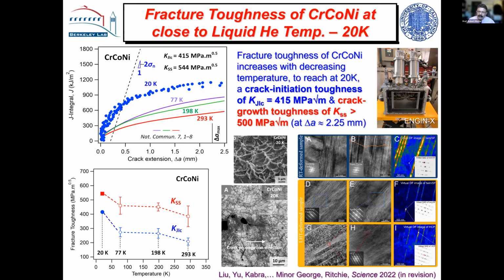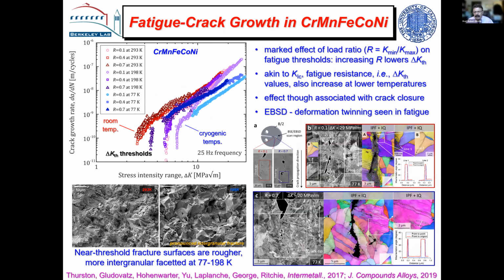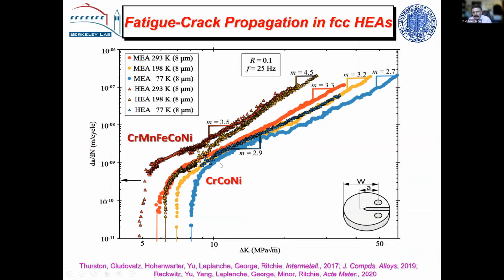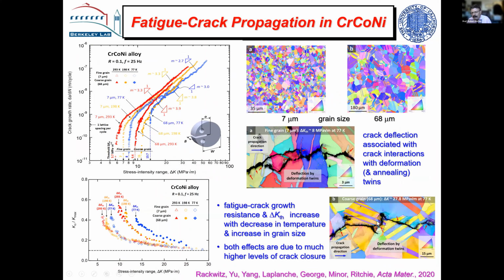There are fatigue effects as well. I'm going to bypass those because we don't have a lot of time. The thresholds in fatigue are higher at low temperatures, but we don't think that's associated necessarily with what I talked about. It's more associated with so-called crack closure. But we do see evidence of twinning, and the twinning can cause crack deflection and things like that. So there is a big effect of this. But if you make the grain size coarser, you roughen the fracture surface and you get much better properties.